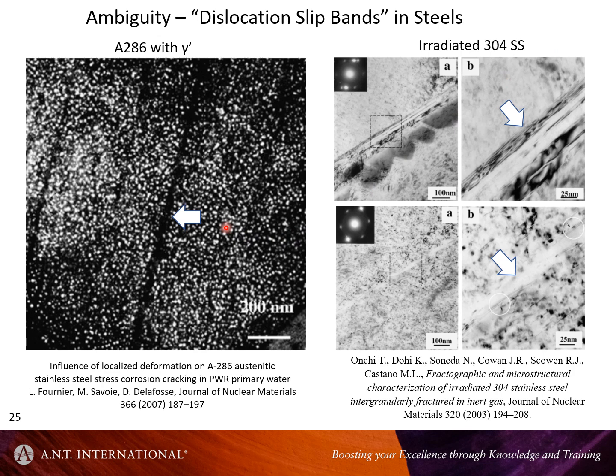But in this particular case, on the left here, these guys looked at this apparently precipitate-free channel and called it a dislocation channel. And they came up with an extremely hard to accept scenario where they said that the dislocations generated by fatigue are sweeping through this channel, which is created as a channel not through sweeping up loops, I'm not sure what it is, and they destroy the gamma prime. Now, the best way to interpret that is that that's a twin, and you've simply tilted the material to an orientation where the gamma prime doesn't show up.